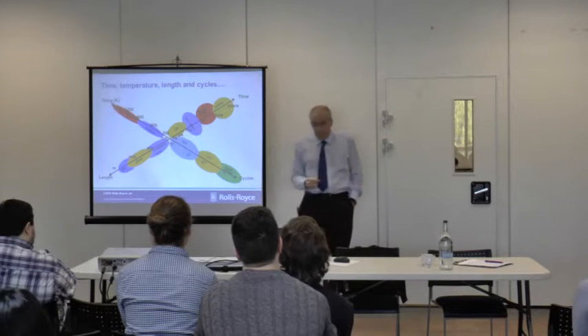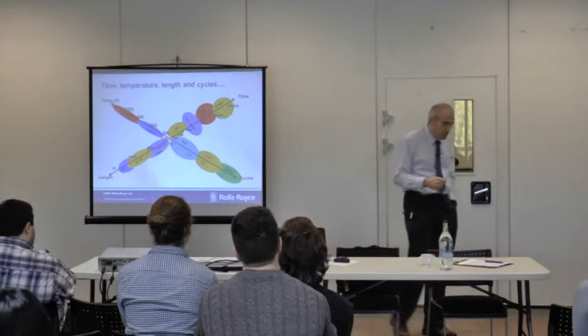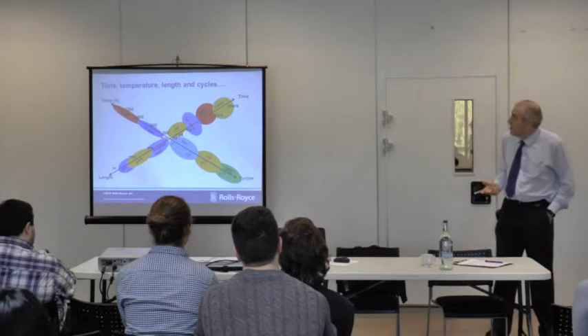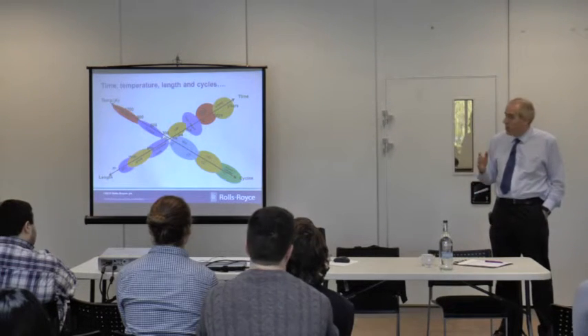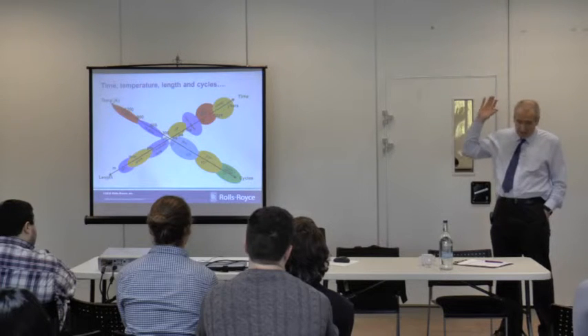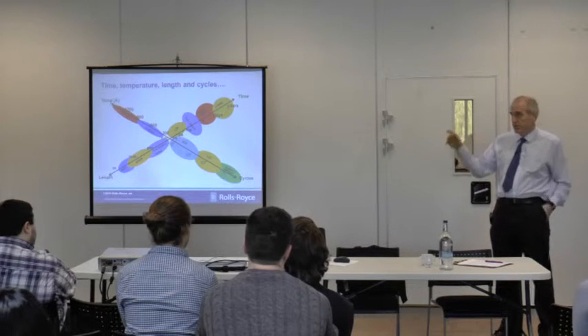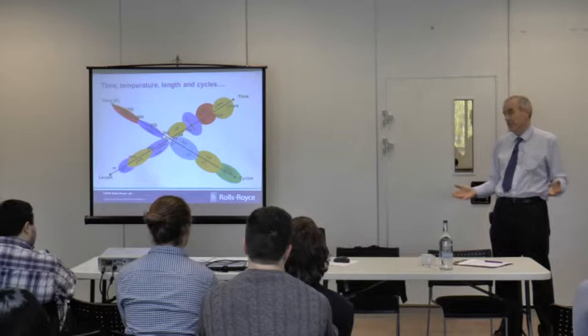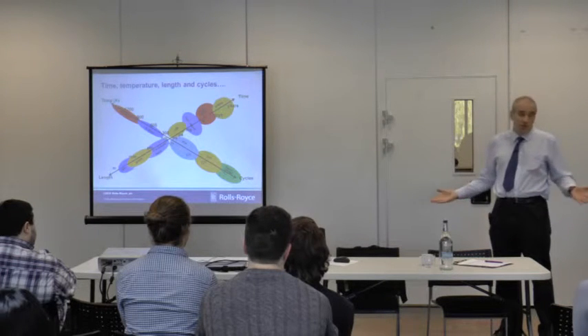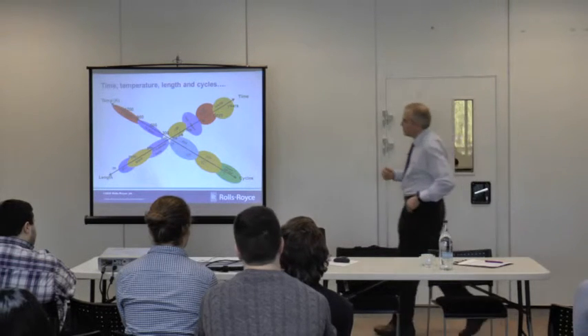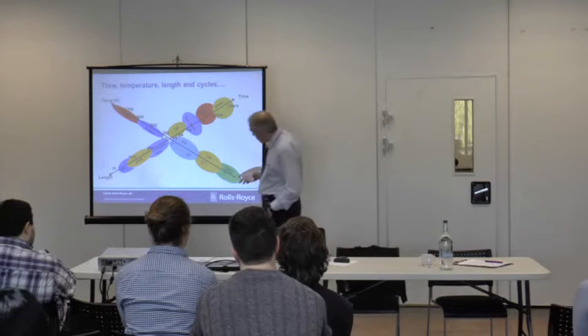And then we also use some fairly advanced processing techniques for metals, one of which is laser peening, where you use a high energy laser. I think it's about a 7 nanosecond pulse we put on the surface. You drive the surface into yield in tension, and then the substrate pulls it back into compression. That optimizes the fatigue behavior.